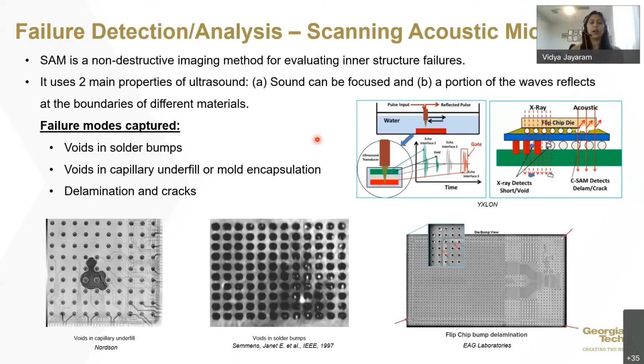Another technique is scanning acoustic microscopy, or SAM. This is also a non-destructive imaging method to evaluate inner structure failures. It uses two main properties of ultrasound: the fact that sound can be focused and that sound waves reflect at boundaries of different materials. So these are the two main ideas behind using ultrasound to detect failures.